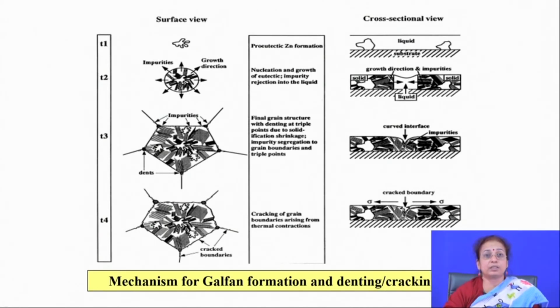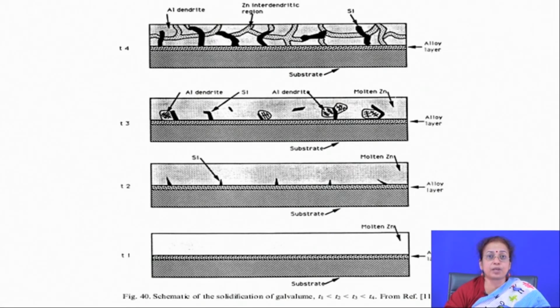But one of the biggest disadvantages of this hot dip galvanizing, where you use Galfan as a bath or 5% aluminum as the bath, is that there is dent formation at the interface basically. This is because when you go on solidifying it, at the middle layer there is still liquid, because it is a eutectic composition. So, the temperature is quite low. If you think of the solidification process, you will find that all other layers solidify, but the last layer, which is still in a liquid state, gets contracted because of solidification shrinkage, and there will be formation of a typical dent mark in the middle of the Galfan coated component. So, there you have to put some extra liquid, so that the probability of this dent formation can be minimized.